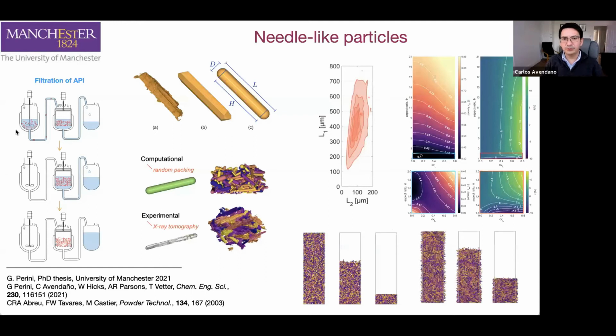And the most common technique to purify APIs is basically crystallization. So after the reactor, we will have the crystallization step. And after that, we need to remove the solvent in the system, and that's typically done by filtration. So we put it in the reactor. We have a filter at the bottom of the reactor. And then by having a vacuum pump, we can create a pressure drop, and then all the liquid will disappear.